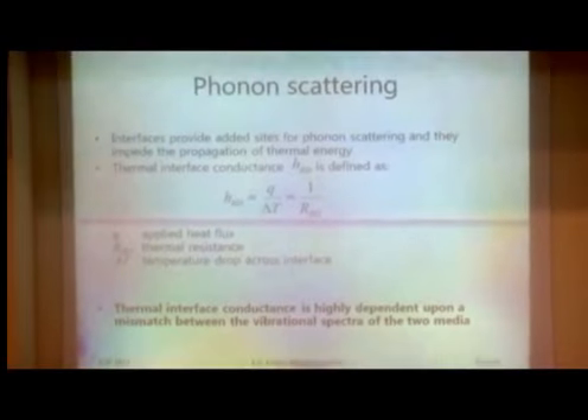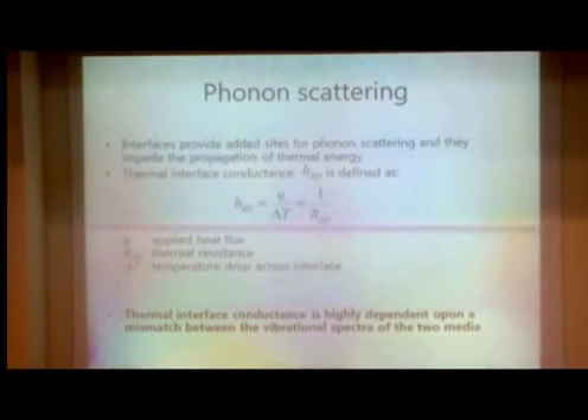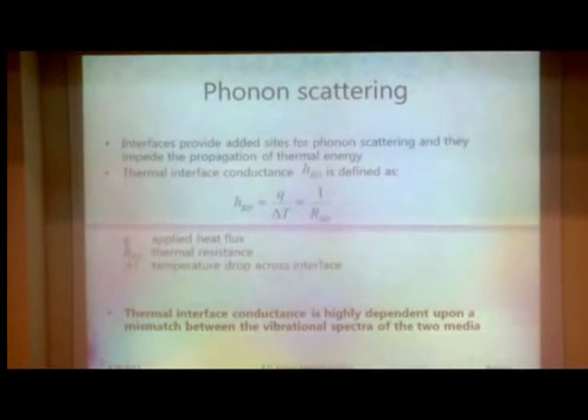The thermal interface conductance is highly dependent upon a possible mismatch between the vibrational spectra of the two media. So different media have different phonon vibration spectra, and if they're unmatched, totally different, if they have no overlap, you have a really big resistance for your heat transport.